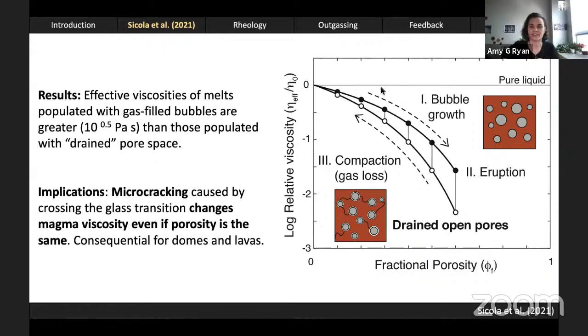That's shown graphically here, where there are two separate viscosity-porosity paths: one defining bubble growth, where you're populated with gas-filled bubbles, and one where those bubbles have been drained of their pore fluid. So this is a critical thing to note when trying to understand what the viscosity of a bubbly melt is. You have to make sure that you're actually working on a bubbly melt, which is not necessarily obvious.